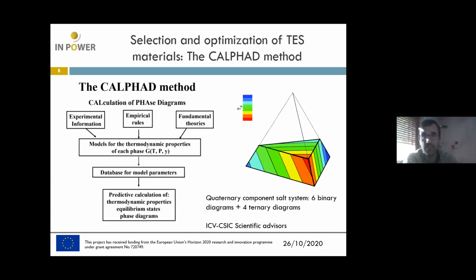Starting with the selection and optimization of these materials, we have to work with the CALPHAD method. It's a thermodynamical method that uses experimental information, empirical rules, and fundamental theory to model thermodynamic properties of each phase of the system. In our case, we worked with four components, 4 nitrates, and four different phases: liquid phases and other solid phases. So we modeled the Gibbs energy of these phases with model parameters that are available in different thermodynamical software. And we predict the behavior and the phase diagrams of all these components. Let's say 6 binary diagrams, 4 ternary diagrams, and 1 quaternary diagram.